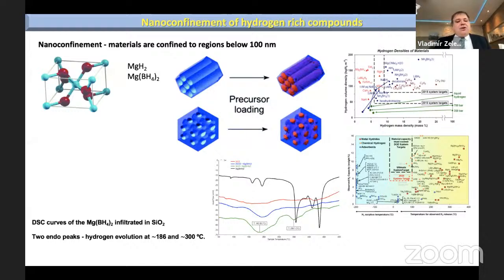And the other approach we are using is a combination of MOFs and hydrides, because MOFs show the so-called nano-confinement effect. Using confinement of different compounds in nanoporous materials, we can decrease the temperature of melting or the temperature of hydrogen desorption from these materials. So the other approach is to put magnesium hydride or borohydrides into our MOFs, or we also use porous silica supports. And we also use some metal doping, 1–2% of nickel. And in this way, we try to reduce the temperature of the hydrogenation of, let's say, magnesium hydride or some borohydrides.